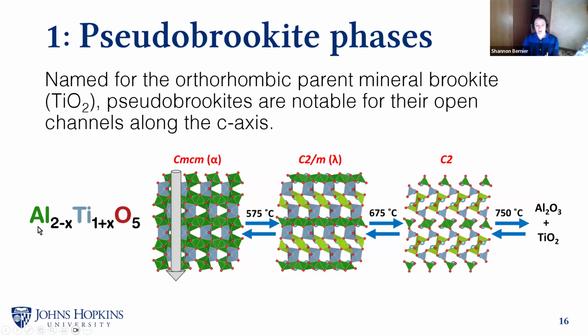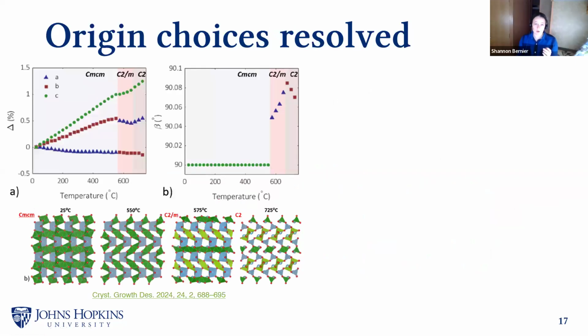So this is an example of an aluminum titanium oxide pseudobrookite that Davor studied. And this one goes through 3 different phase transitions as the temperature is increased before it finally decomposes into aluminum oxide and titanium oxide. In the conventional way of discussing this kind of lattice expansion and phase change, we would look at 2 different plots to interpret what's going on.